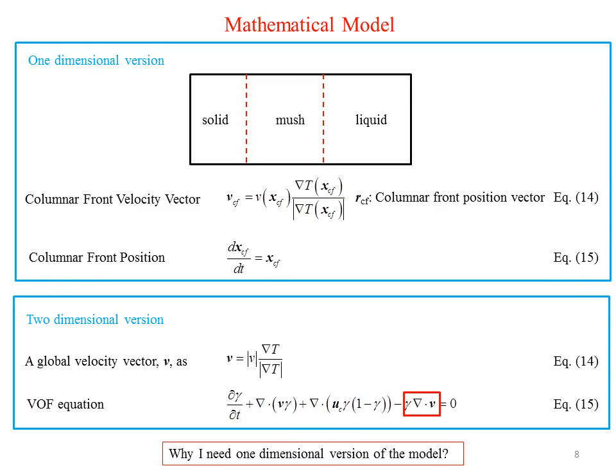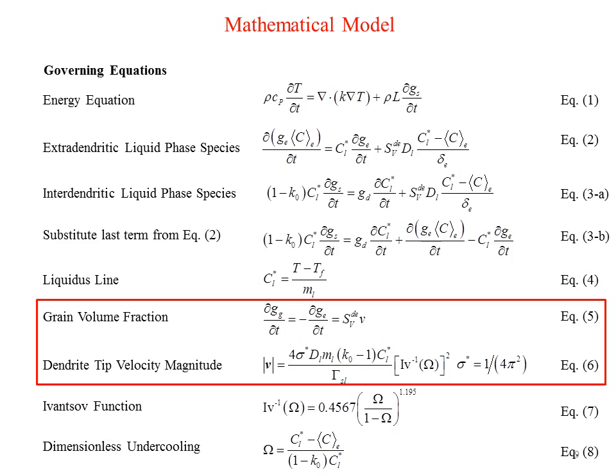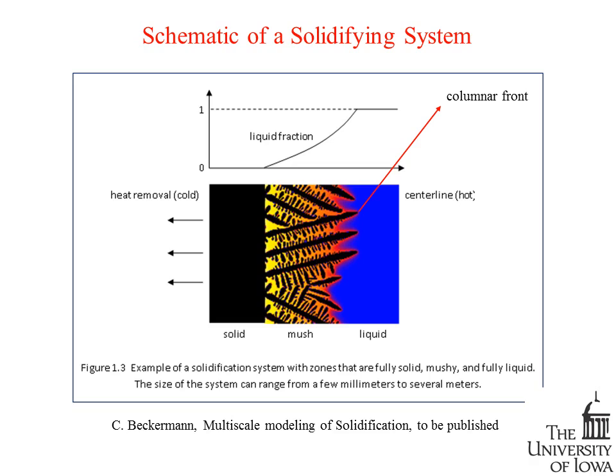If you look at this equation, it is not global, meaning that it is valid only in some parts of the simulation domain. If I implement this equation in, for example, the liquid region, I will get absolute garbage. It's not valid there. So during the simulation, to decide whether I have to implement this equation or not, I need to know the position of this solidification front. After I know that, I can easily say, implement that equation in this region, but not in that region. So in order to make that decision, I need an algorithm to track this solidification front.